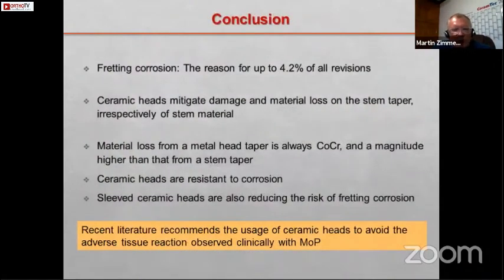So this brings me already to the conclusion of my presentation. You have to remember that fretting corrosion occurs in up to 4.2% of all cases of revisions. The ceramic heads can mitigate the damage, and the material loss comes mainly from the stem taper and is independent of the stem material. The material loss from the metal head comes mainly from the taper of the ball head, and that's always cobalt chrome, and the magnitude is higher than that from the taper of the stem.